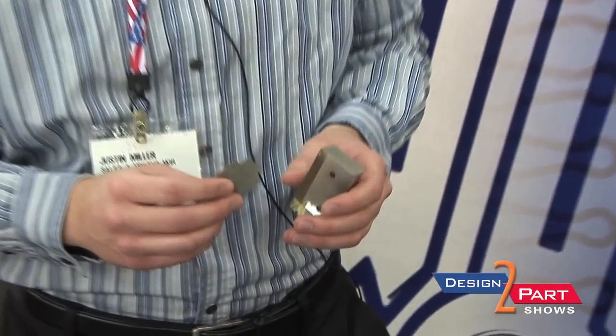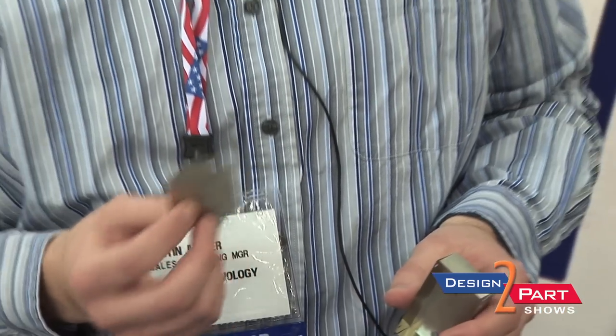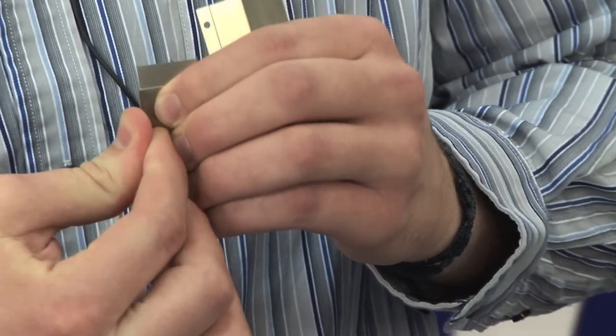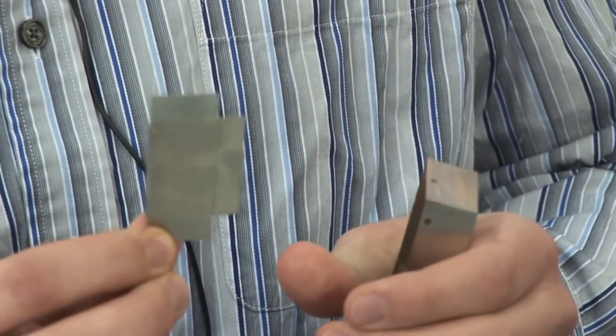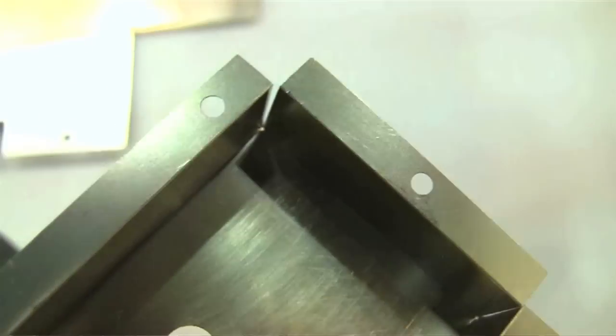These right here are shields. This material is called nickel silver — it's a copper-nickel-zinc alloy. The advantage over copper is that when you use it on a circuit board, you can solder the base material without needing tin plating. We also put half-etched lines in there so you can fold the sides up and make a box. Instead of needing hard tooling, the half-etched line helps you get a straight edge so you can achieve a good 90-degree angle.